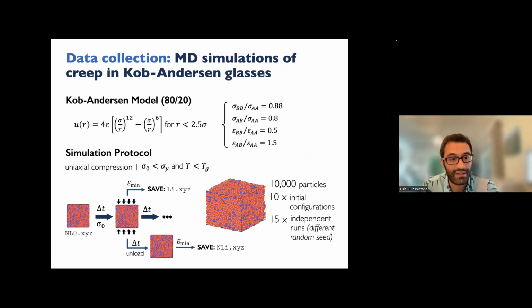So what we are using is a Kob-Andersen model. This is a glass model system. These are two types of particles interacting through a Lennard-Jones potential, this 12-6 Lennard-Jones potential. And the reason there are two particles interacting through these interaction parameters is that if you have a monodispersed Lennard-Jones system, it's going to crystallize, right?